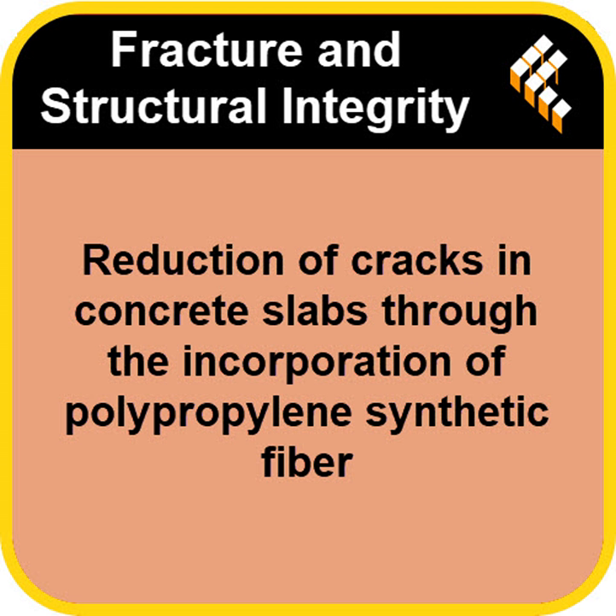Right. This is the true test. Does the early advantage hold up? This is where they applied their crack reduction ratio formula to find the absolute optimal dose. Okay, let's break down that 28-day data, starting with crack width. You could argue that's the most important metric for a building's lifespan. I would agree. And here, the DM02 mix, the 1,000-gram dose, was the clear winner. It achieved an 18.41% reduction in crack width.